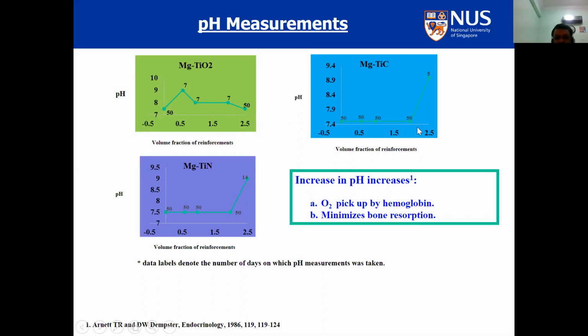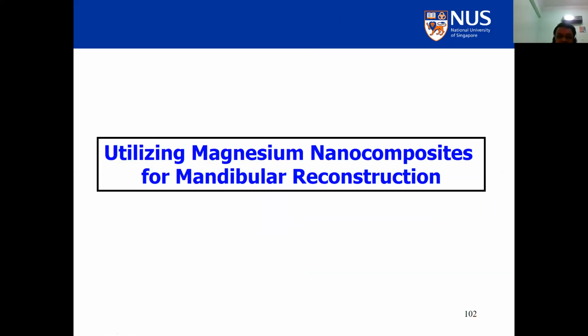Similarly, for TiC, I will choose magnesium 2% TiC. And for TiN, I will use about 2% TiN. So I will choose one of these materials with a specific composition. And obviously, slight pH increase is okay because it can help in oxygen pickup and it can minimize the bone resorption, but too much pH can lead to microtoxicity.